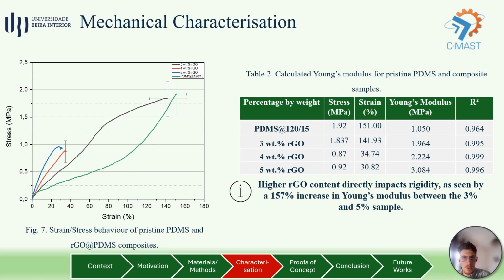In the mechanical characterization, we employed the universal testing machine to carry out tensile tests on both pristine PDMS and the composites, and the 3% rGO samples showed stupendous performance when compared to the others, with their average strain and stress values being the closest to our pure PDMS configuration. In addition, a higher rGO content was directly related to greater rigidity and brittleness, which was both seen during the manufacturing process and now confirmed by the calculated Young's modulus.